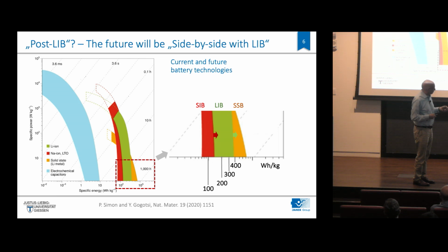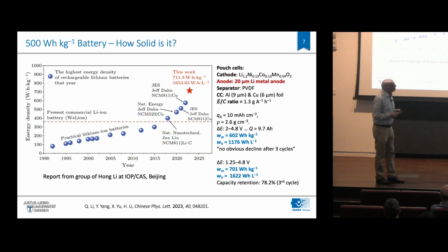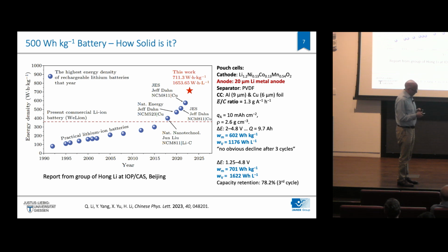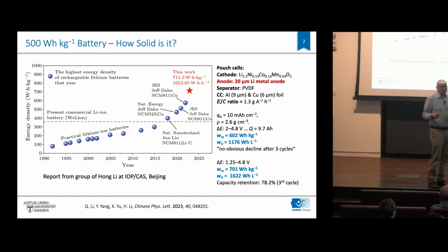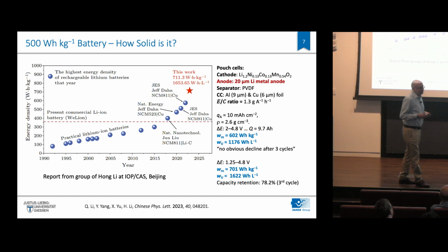an interesting market, of course. Now, this is a paper from a good colleague, particularly from China, from Hong Li, who in a non-battery journal, the Chinese Physics Letters, had a very nice paper where he showed, okay, as a function of the year, what is the specific energy? You see here again the 400 watt-hours per kilogram, which is marked here roughly by the red line. And this limits somehow the development of current lithium-ion battery technology. And that is cells that use a graphite anode and oxide cathodes, roughly, and typical liquid electrolytes. So that's typically a limit that can be overcome.